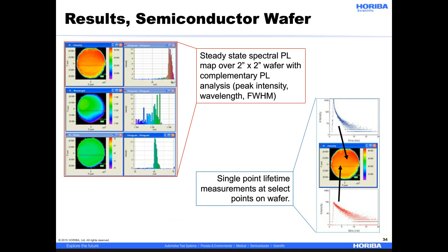The first set of results I'm going to review were recorded on a 2-inch by 2-inch indium phosphide semiconductor wafer. The set of data you see on the left-hand side of the screen corresponds to steady-state PL mapping spectra over the entire surface. In this case, I have shown 3 graphs plotting different PL parameters. The top graph shows a map of the PL intensity, the middle graph shows a plot of peak PL wavelength, and the bottom graph shows a plot of the peak width.